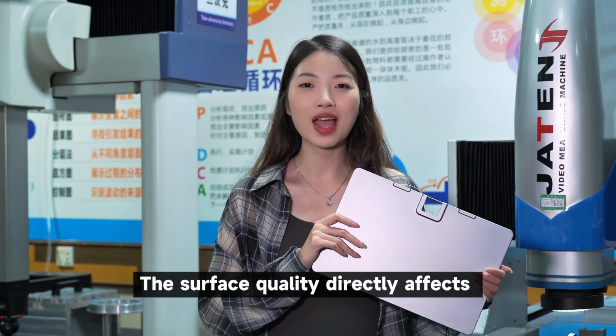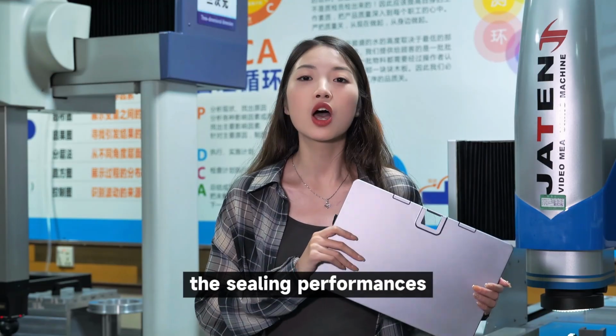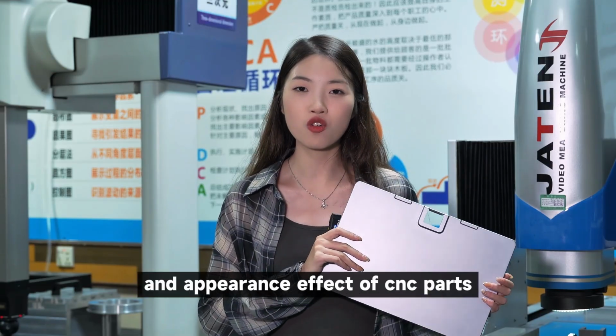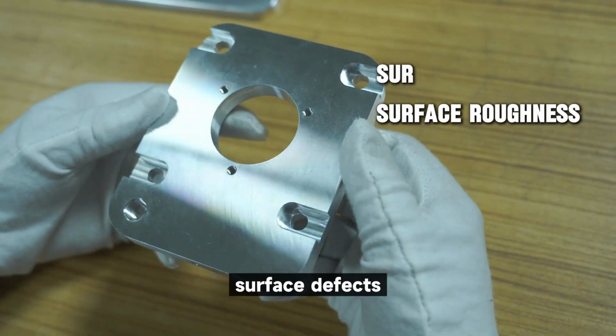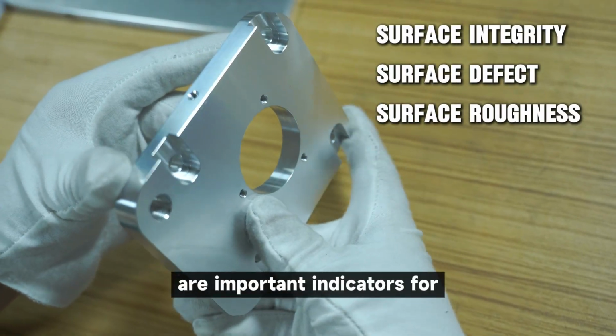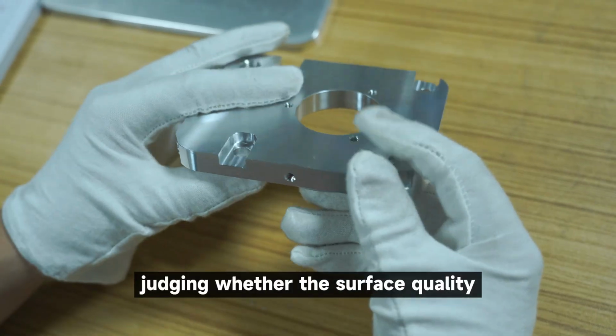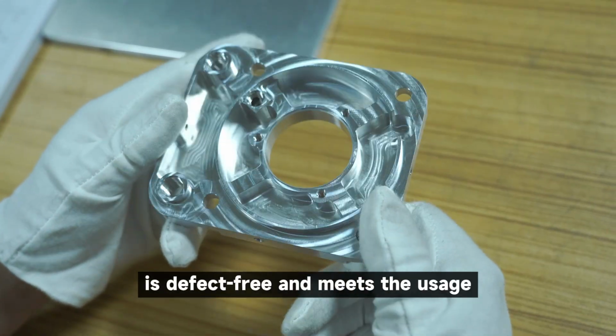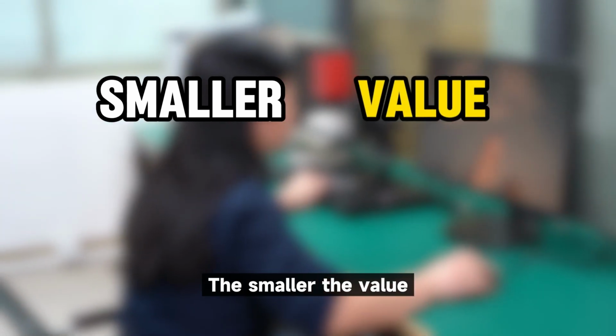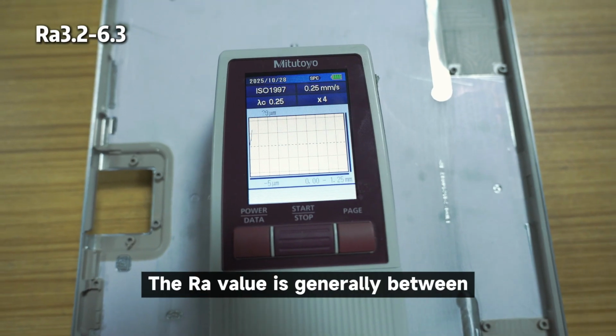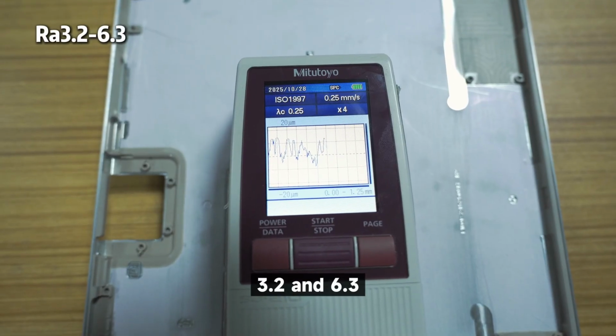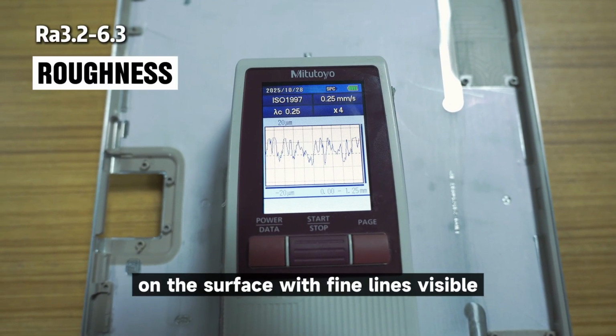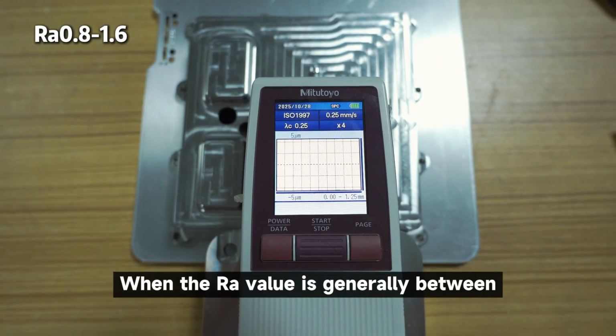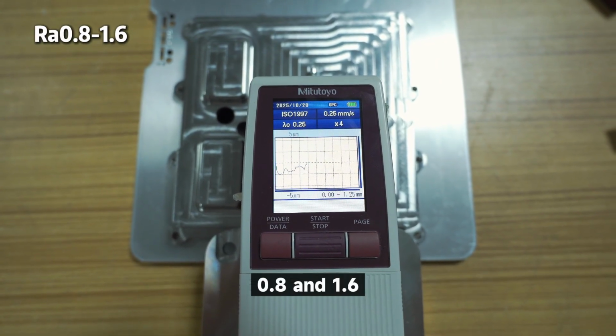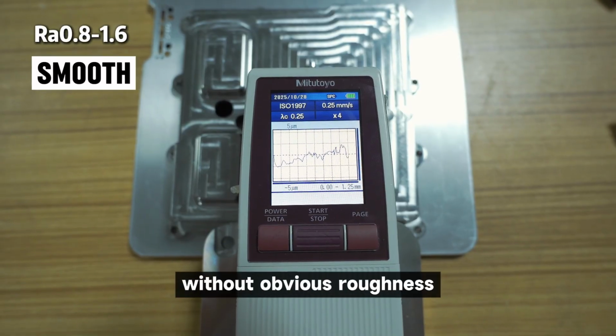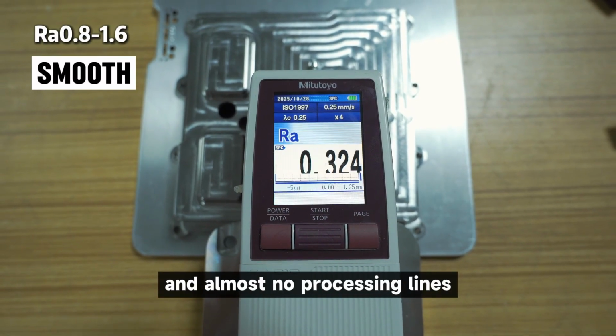The surface quality directly affects sealing performance, wear resistance, and appearance effect of CNC parts. So surface roughness, surface defects, and surface integrity are important indicators for judging whether the surface quality is defect-free and meets the usage requirements. The smaller the value, the smoother the surface. The RA value is generally between 3.2 and 6.3, and there will be a distinct roughness on the surface with fine lines visible. When the RA value is generally between 0.8 and 1.6, it will be fine and smooth without obvious roughness, and almost no machining lines can be seen.